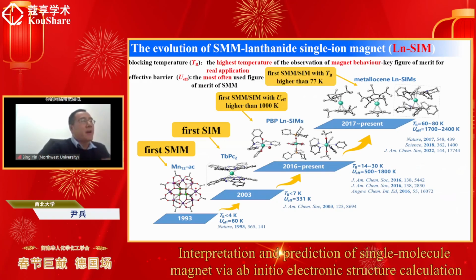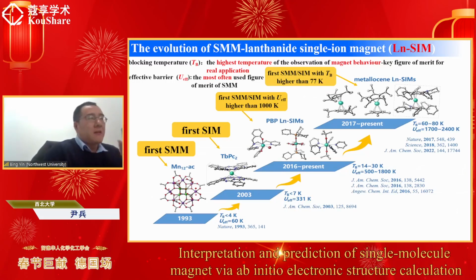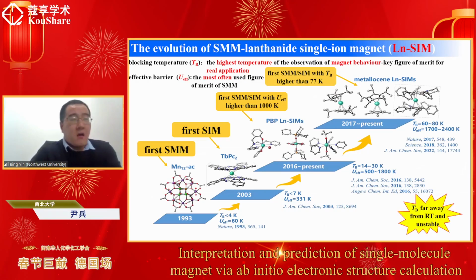For example, the first system with an effective barrier higher than 1000 Kelvin comes from lanthanide, especially a dysprosium-based single ion magnet. And the first single molecular system with TB higher than the liquid nitrogen limit, that is higher than 77 Kelvin, also comes from a lanthanide-based single ion magnet. However, even the highest TB now is still far away from room temperature, and all these systems with the highest TB currently are unstable in the presence of oxygen and moisture.